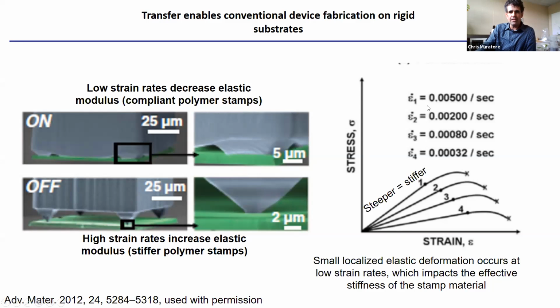So you can see that this strain rate 1 is higher than the rest. It's like a factor of 20 higher than the last one. And you can see what happens to the stiffness of the material. It gets less and less stiff as that rate gets smaller and smaller. And so I'm a chewing gum addict right now. And if we were in a classroom, I'm chewing some gum right now. I could take it out of my mouth and stretch it. It's kind of gross, but I could stretch it out at a slow rate. But if I throw it against the wall, it's just going to bounce off, like I threw a rock at